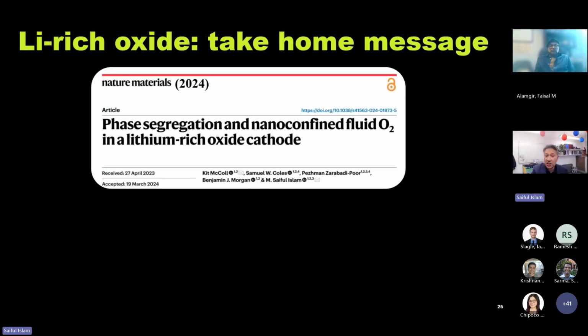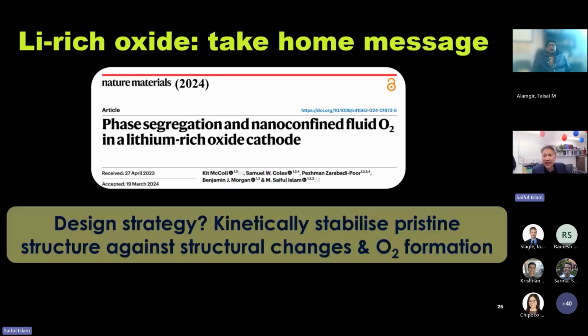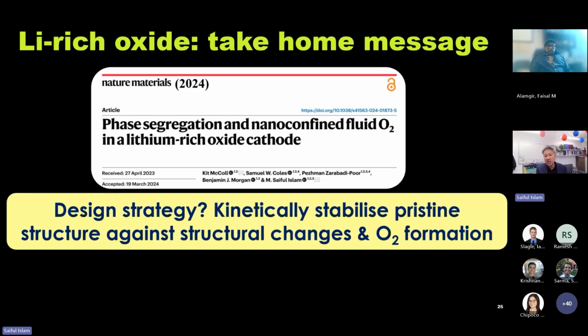So what is the take-home message? This was published in 2024 in Nature Materials. We call it phase segregation and nano-confined fluid O2 in lithium-rich oxide cathode. But what are the implications? The implications are we want to kinetically stabilize a pristine structure against, I stress, against structural changes and O2 formation. We do not want O2 formation if we want reversible high energy density lithium-rich cathodes.